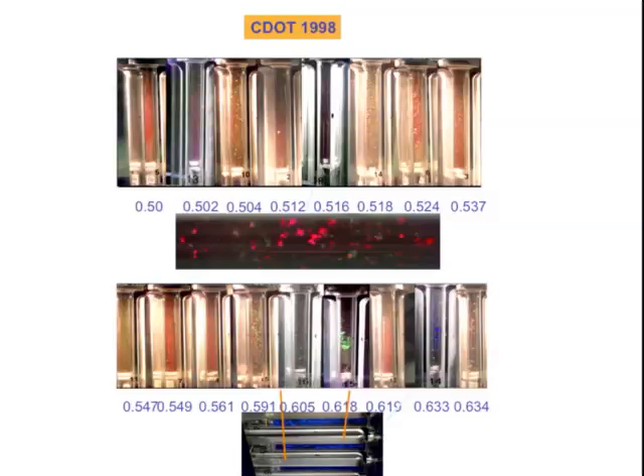And what the phase diagram shows is below 50% is liquid, above like 50% you're starting to get crystals. Actually, when you look at how the crystals grow, they grow like snowflakes. One of the things we found out is the model at the time for how the crystals would grow is like a spherical shell growing out. That's a standard model for nucleation and growth. But there's an instability which you could actually calculate once you know it's there, which means dendrites shoot out. So that's something we found, but that's not that spectacular.